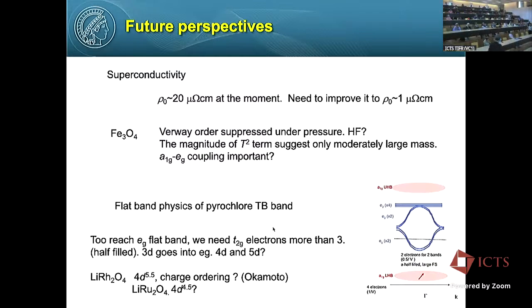Very interesting. In fact, I found a lot of similarities with V2O3 we discussed yesterday. But what I was wondering is why magnetite actually charge orders, even though at a certain temperature, but lithium vanadate doesn't. Is it because that's inverse spinel versus normal spinel? Because that's an inverse spinel. This is of course unlike V2O3,